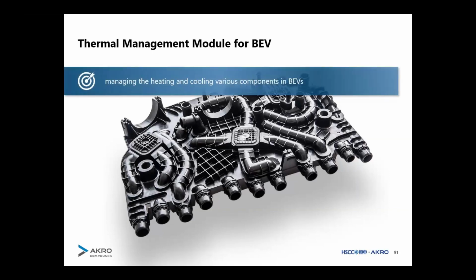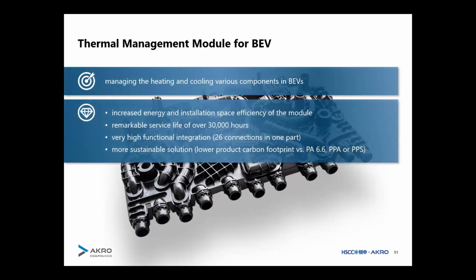So, we explained what the task of this part is, but what are the values for the customer? First, by bringing all this together in one module, we have a strongly increased energy efficiency, but also installation space efficiency. And this was tested for a lifetime of 30,000 hours. And we see here we were able to bring 26 different parts into only one part in the end. And of course, it's easy to acknowledge that this is a much more sustainable solution already material-wise, and also compared to different materials like nylon 6,6 or even more expensive grades like PPA or PPS.